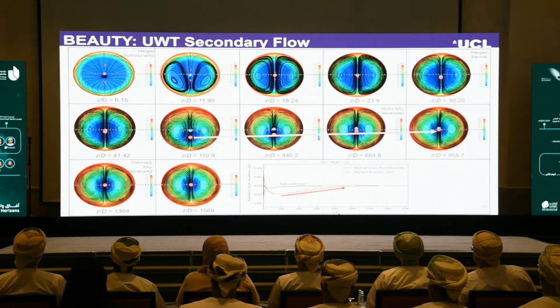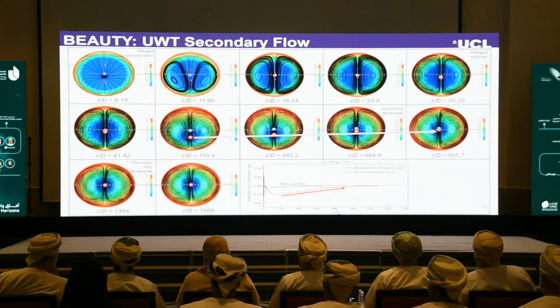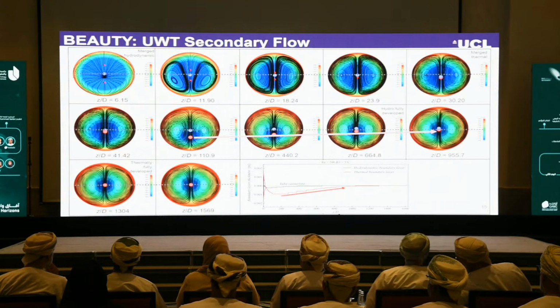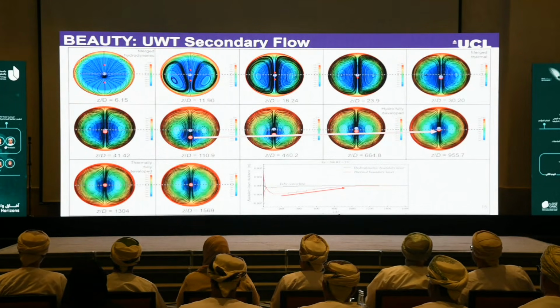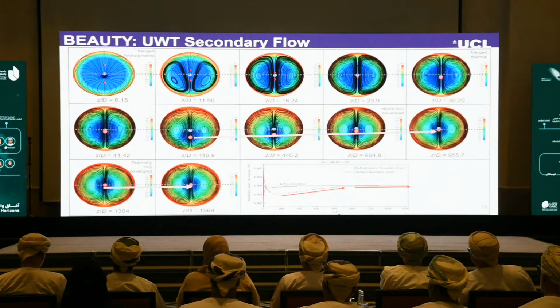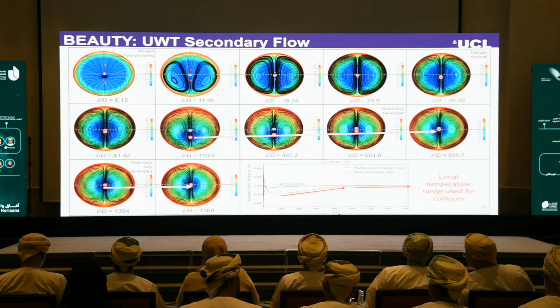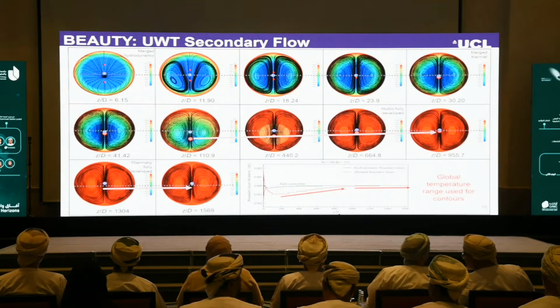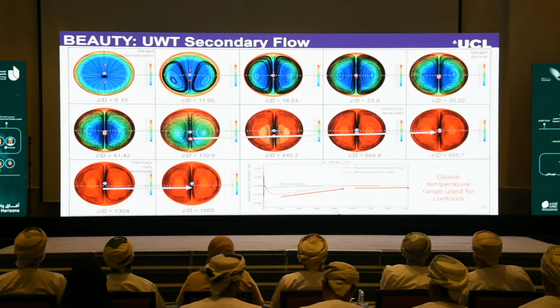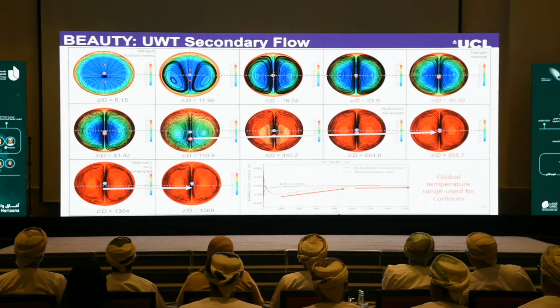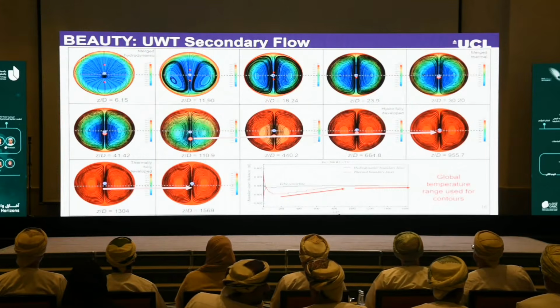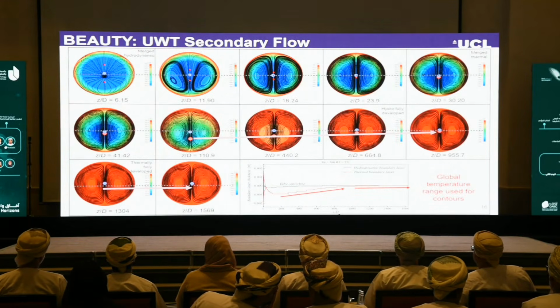So you might at this point think, okay, but what's the big deal? Because we still have temperature gradients, so we still have this convective behavior going on. But it should be noted that this is the local temperature range. So it basically just looks at the local temperature range at this specific cross-section. If we plot this in terms of global temperature ranges, we see that towards the end of the heat exchanger, there's a very negligible temperature gradient, and therefore we can no longer benefit from any of these mixed convective effects.